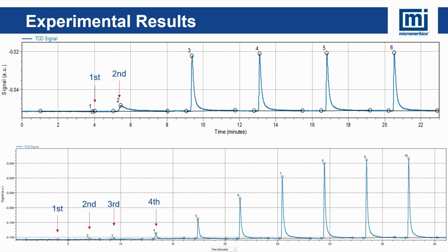A key takeaway is that the cleaning process after the activation step is crucial. Any trace of oxygen can reoxidize the material and react with hydrogen, which will affect the measurements. Hence, if your gas cylinder is below a certain threshold, it may be a good idea to replace it.